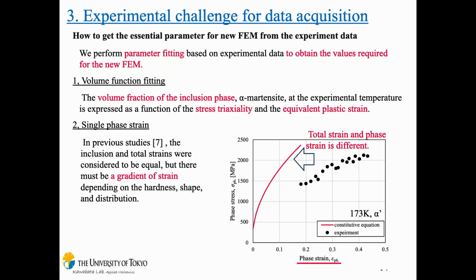Okay, so next we try to get some values to use in the FEM from the experimental result. We have to do two processes. The first is volume fraction fitting. It means that the inclusion volume fraction should be expressed as a function of stress triaxiality and equivalent plastic strain. And the second process is to get the single phase strain. We don't know the single phase strain directly from the experiment, so we have to get this. As a result, we can get the single phase constitutive equation.